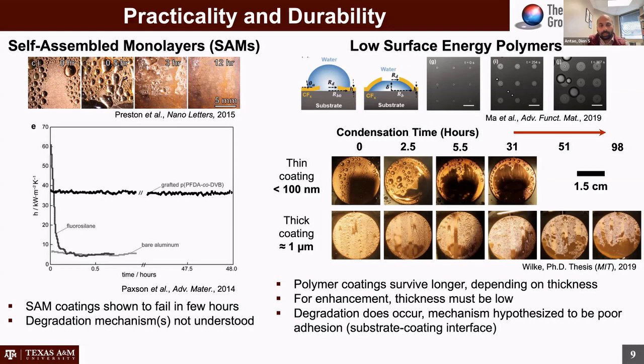Of course, on the other side, with these low surface energy polymers, you also have similar and different degradation mechanisms. There's the work out of Ninad's group that has looked at one potential mechanism, which is this formation of blisters and delamination. And similar work I've seen out of Evelyn Wang's group at MIT. One aspect that I've not covered here is some of the recent work which has been done out of Simon Dye's group, among others, on a slippery surface that does not involve a liquid lubricant. They're liquid-like materials. But in essence, those surfaces too haven't been tested on long time scales for durability.